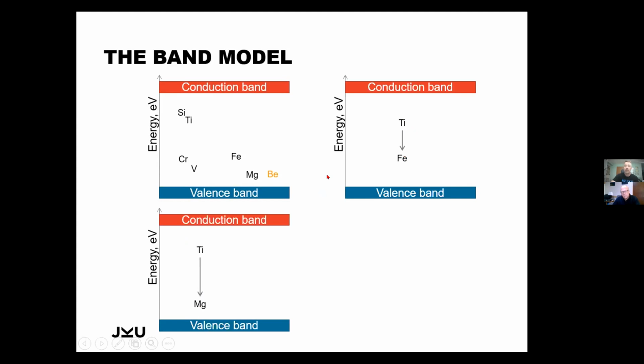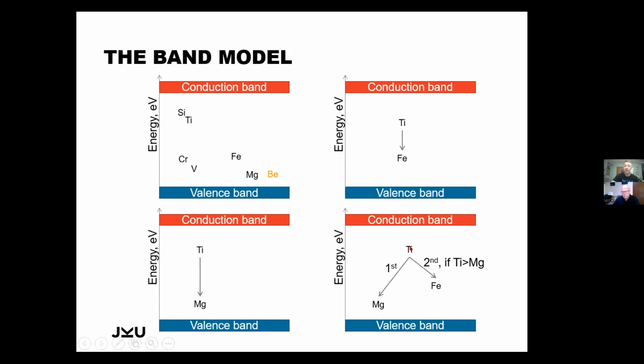So the problem now is, as long as there is magnesium, titanium will pair with the magnesium and not with the iron. So you need to understand the complete chemistry that in the first step, titanium will pair with magnesium, and only if the concentration of titanium is larger than the one from magnesium, there's titanium left to interact with the iron. And only if you record the concentration of all these elements, you can see how the charge transfer acts. If there is titanium and magnesium, you have to measure both concentrations to create the free or active titanium. And you have to have the iron and a couple of other elements to see what is left in transition elements that can undergo these transitions.